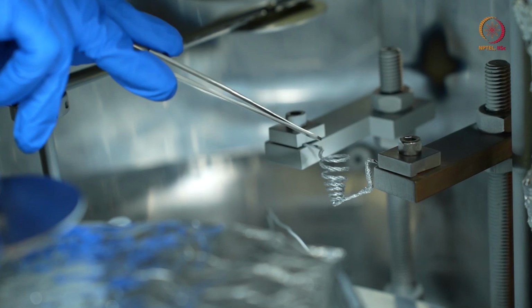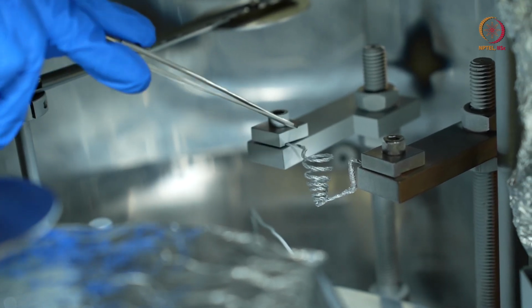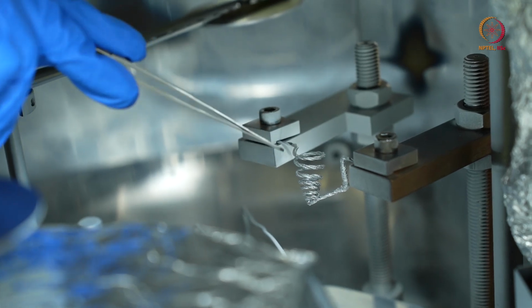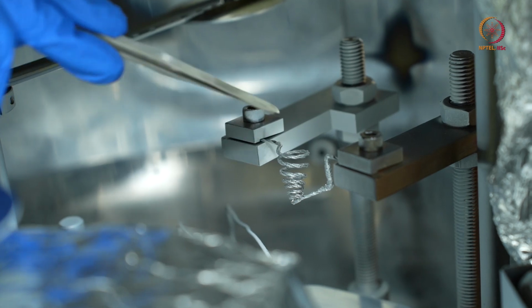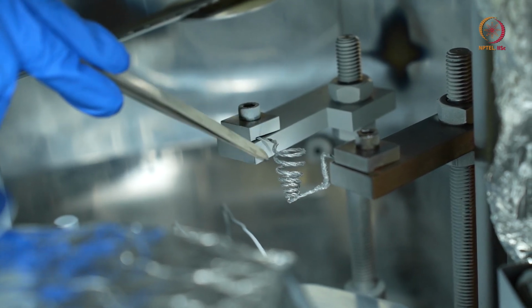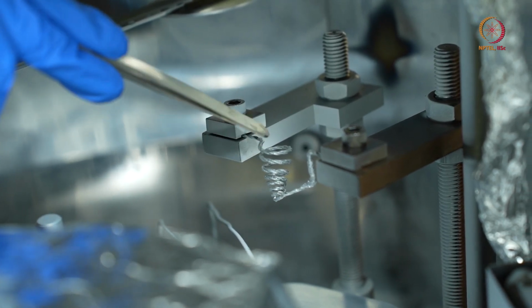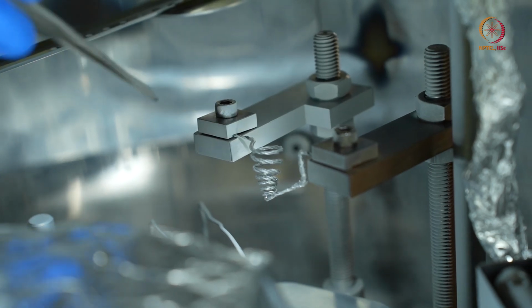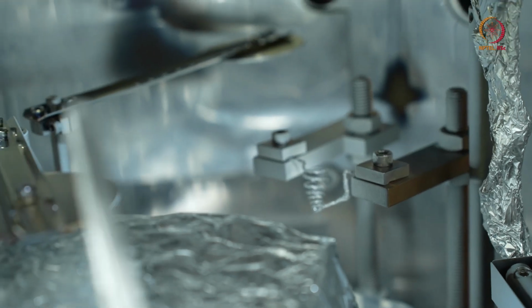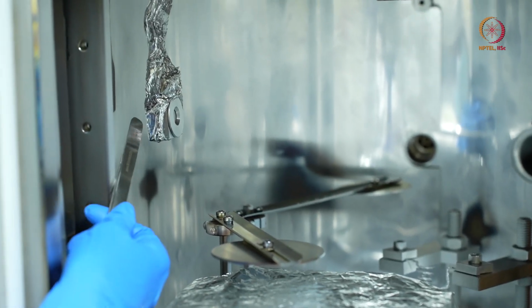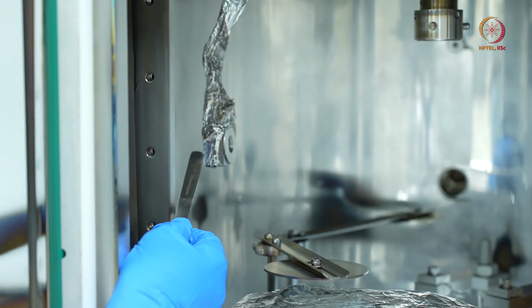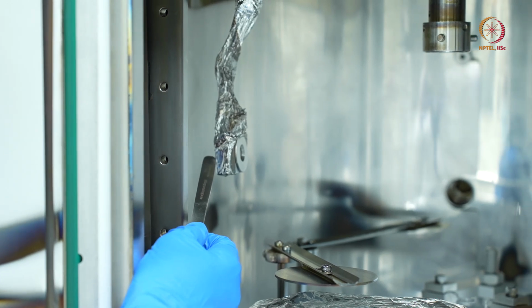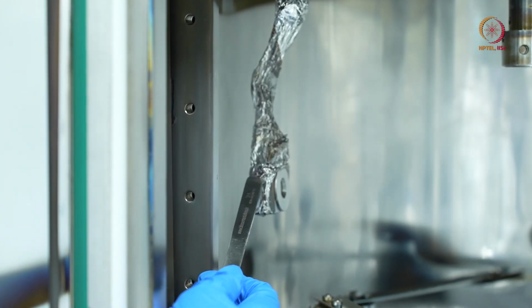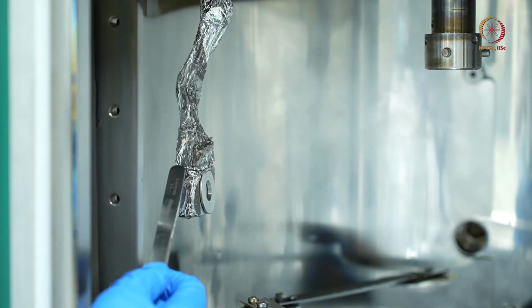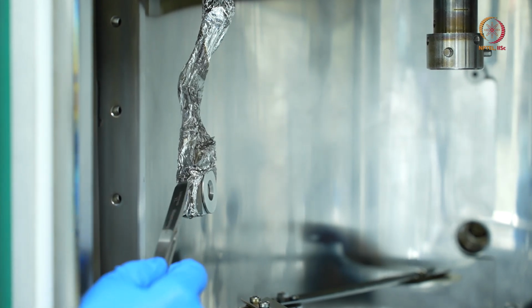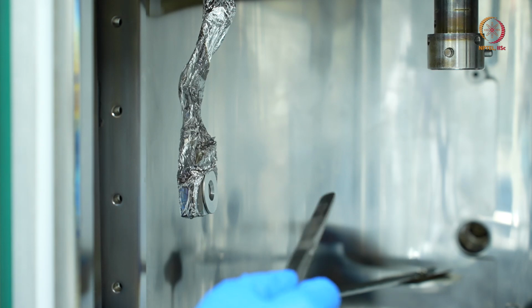You might feel that once this material melts, it will come out of the basket, because there are gaps in the basket. But because of the surface tension and wettability with the tungsten, the material will not fall down, and it will just stick to the walls or the coil of the basket. Now we'll see the DTM, which is here. It is a quartz crystal monitor. It has a quartz crystal inside it, which has its resonant frequency. Once some mass gets deposited on that quartz crystal, its frequency will change, and the change in frequency will be converted to the amount of thickness deposited in that run.